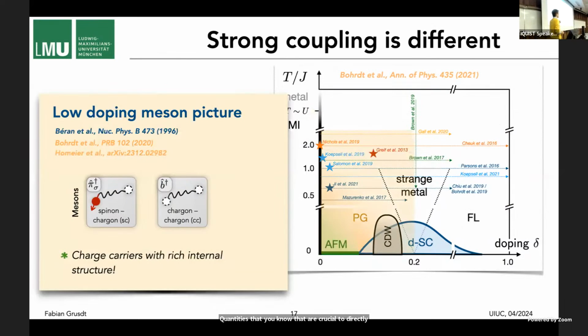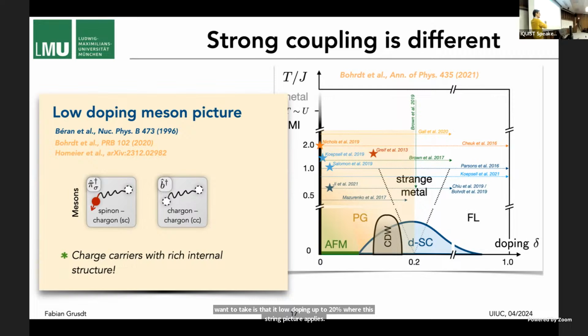Okay, now let me turn a little bit more to the story I want to tell you in the picture we developed, starting from the cold atoms. And so the perspective I want to take is that at low doping up to 20%, where this string picture applies, the charge carriers are these string-like objects. And as I already advertised, we can understand that as confined or bound states of a spinon and a chargon. It's a spin and a charge excitation connected by a string. We're talking about short strings, three-ish lattice sites. And something I will mention later on is also that there could be other objects too that we find some numerical evidence for, which is charge-two bound states. That's basically a pair of two holes connected by a similar type of string. But in those experiments, at least so far, there are no signatures of these hole strings. Temperature would certainly be a problem for that.